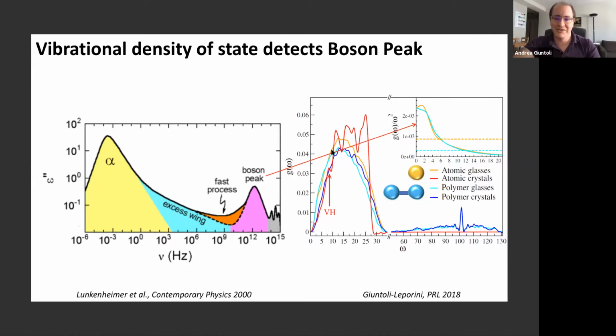And from the vibrational density of states, you can see that the glassy systems have some additional soft modes here that are not present in the crystals. And if you plot the density distribution divided by omega squared, you see the boson peak, which is the same for our polymer and atomic glasses, despite the fact that their elastic properties are different, so their Debye levels are different.